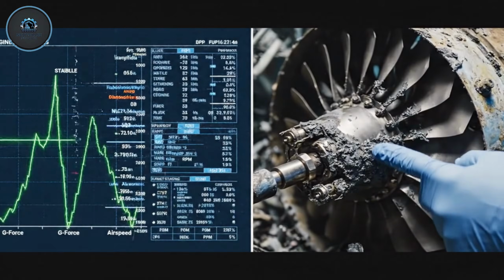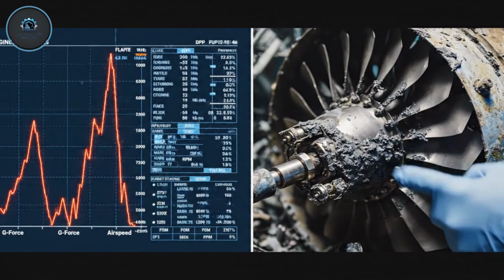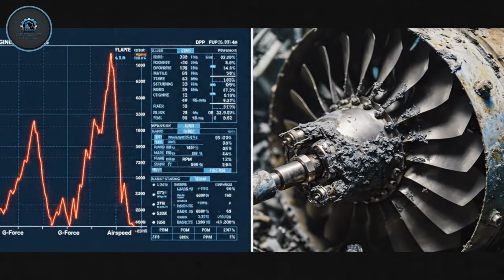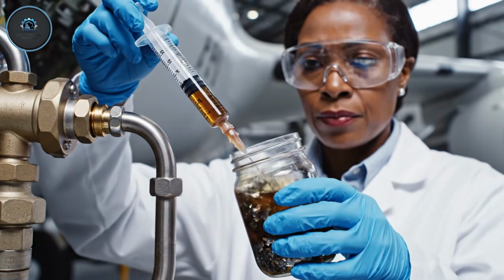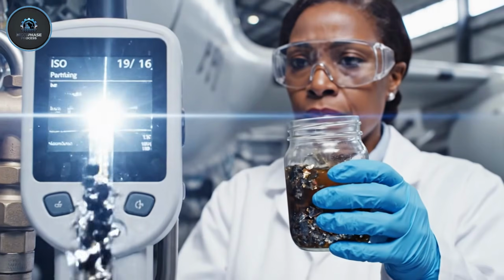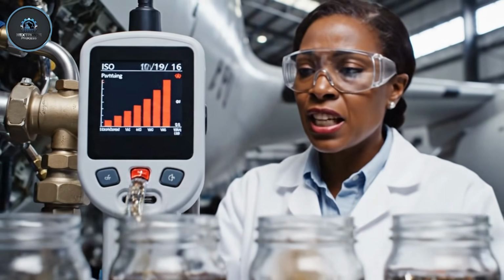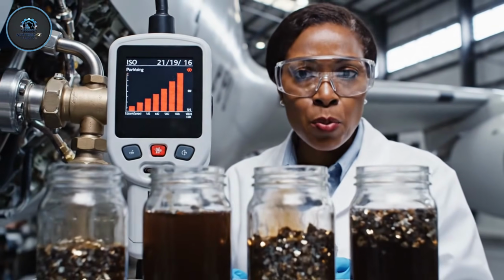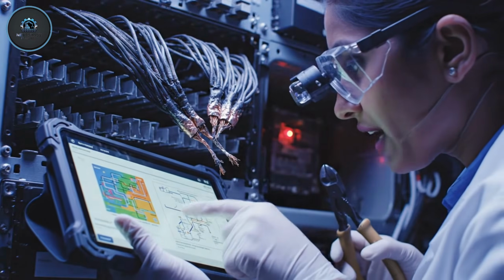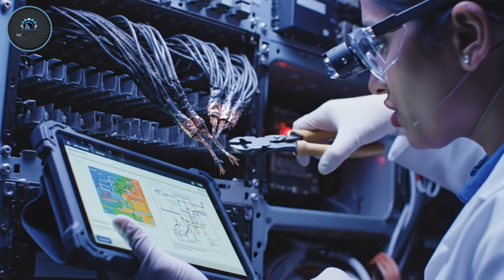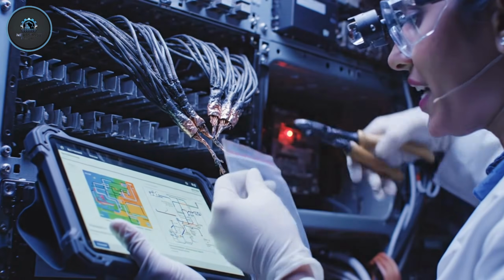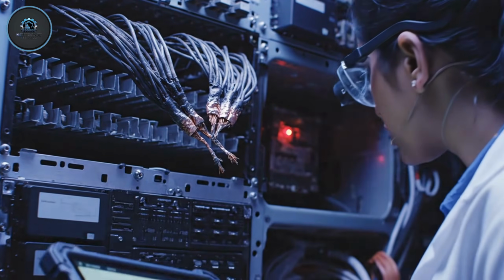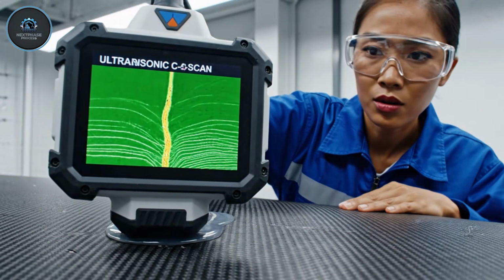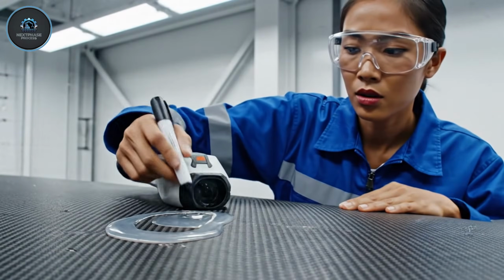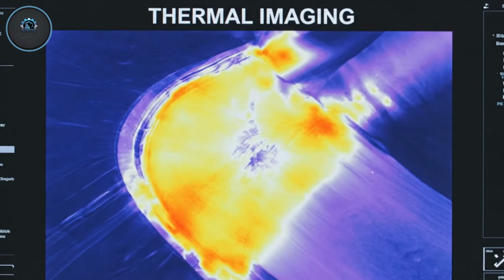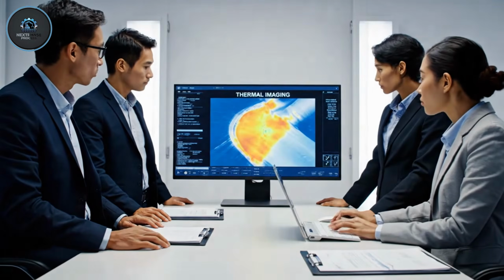When flight data indicates a high-speed impact, the physical wreckage shows corresponding damage patterns. Particle count, ISO code 21/19/16, exceeds acceptable limits. Significant contamination across multiple sample points. Arc initiation point identified, wire bundle 7 alpha 3, insulation failure, propagation across approximately 80 centimeters affecting multiple critical circuits. Extensive delamination. No external indication. No maintenance record of previous detection.